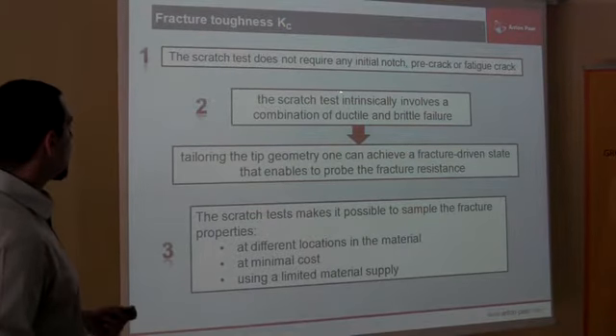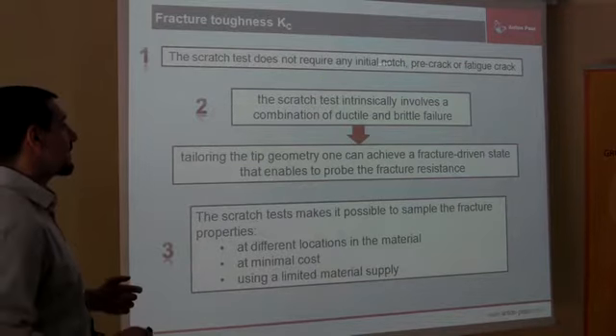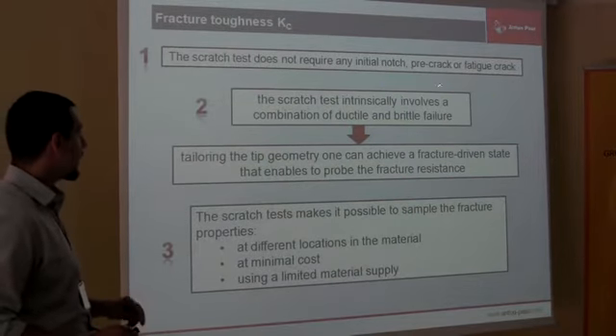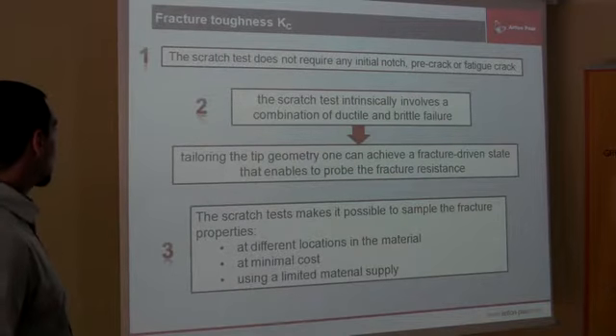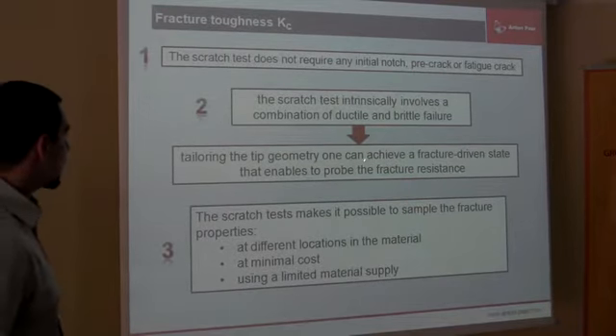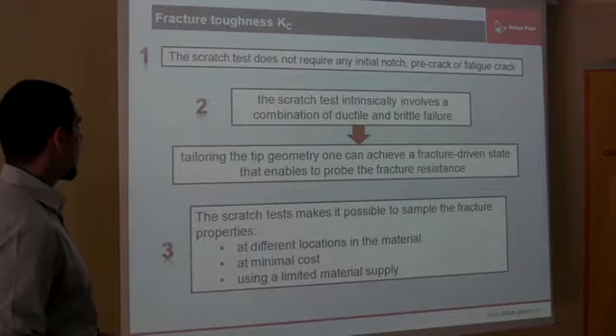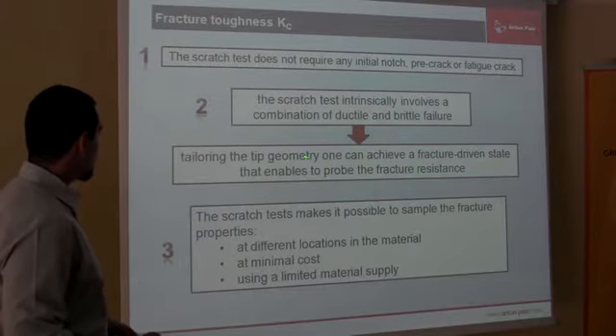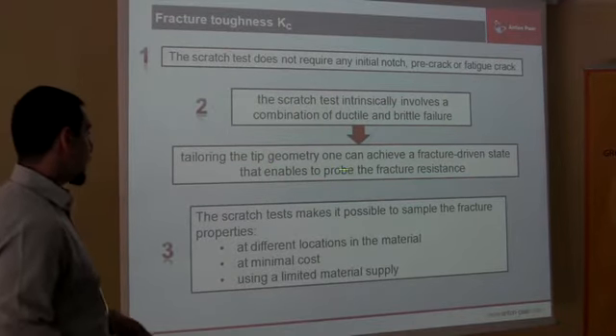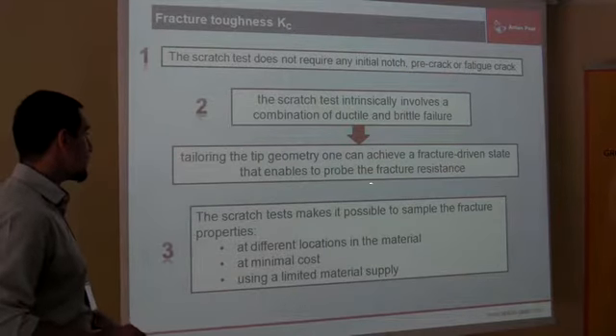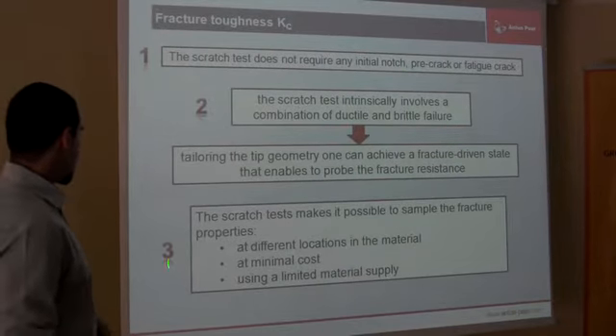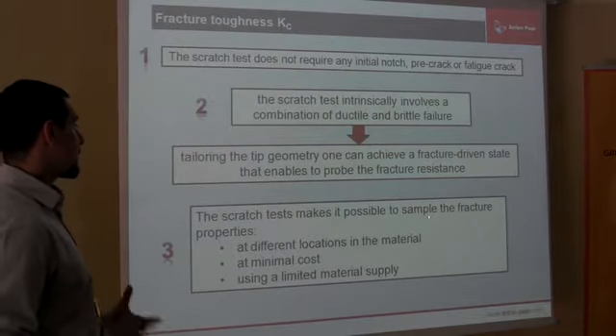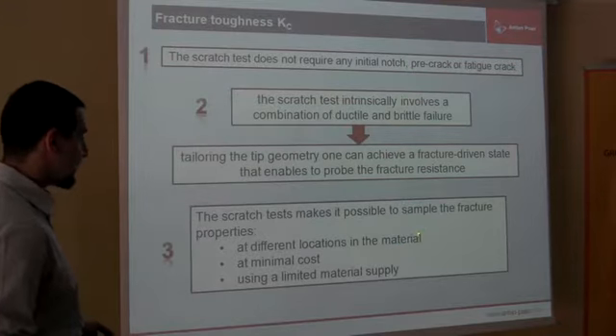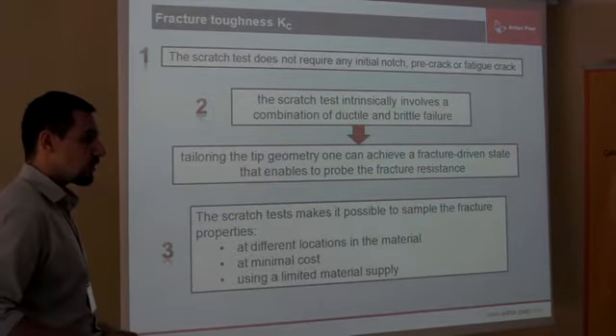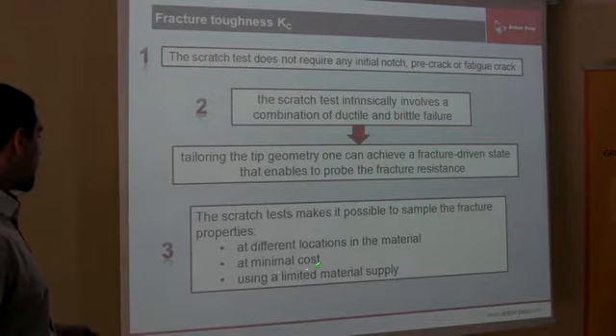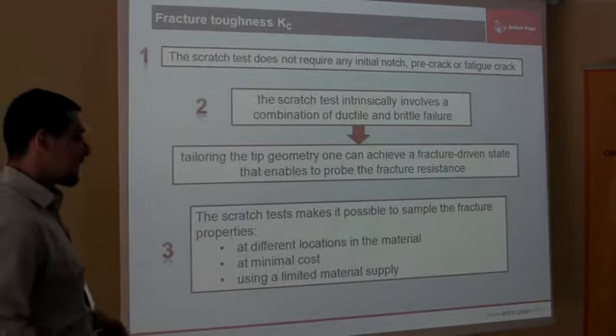The important thing is the scratch test does not require any initial notch or pre-crack or fatigue on the sample. In the same way in which we have to choose the initial notch with macro tests, here we have to choose the tip geometry to achieve a fracture-driven state that enables us to probe the fracture resistance. With a scratch test, it is possible to sample the fracture property in different locations in the material, so we can also test inhomogeneous materials, with minimal cost and a limited material supply.